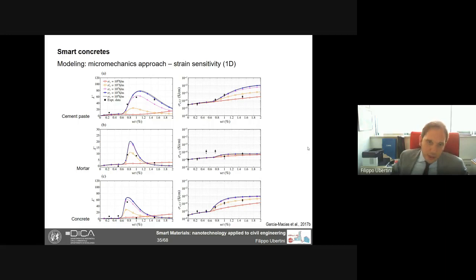And here we can show that we can well predict the gauge factors that we get from experiments, again with black squares, if we introduce the agglomerations besides the twisting of the nanotubes. And we see from the experiments that actually we get the maximum values of the gauge factors at the percolation.